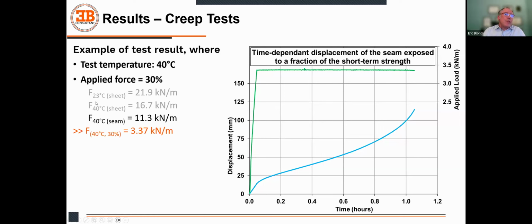So from initial value force of the sheet at 23 Celsius of 21.9 kilonewton per meter, so that's the design value we would normally consider for the sheet. We reduce it to reflect the temperature of 40 Celsius. So we are down to 16.7. That's test data. Then the seam strength that we get at that temperature is in fact limited to only 11.3 kilonewton per meter. So we apply 30% of this value, which gets us down to 3.37. So it's much lower than the initial value, but that still reflects the test condition that we've decided here.